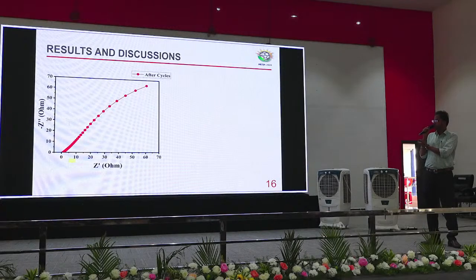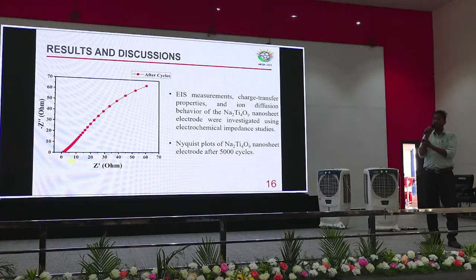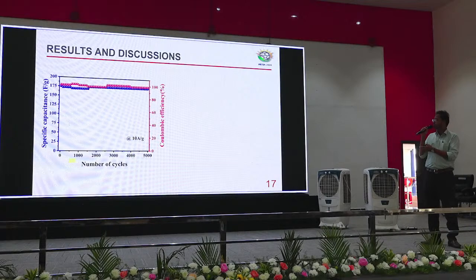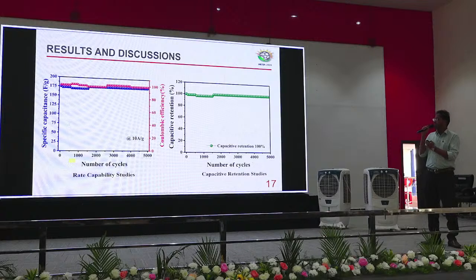So after that we move on to impedance studies. After finishing 5000 cycles, we get the Warburg region from those studies, and the Nyquist plot was calculated. Then we move on to rate capability studies. For rate capability, we use 10 ampere per gram, a higher current density, and cycle for 5000 cycles, and we get 100% Coulombic efficiency. Then capacity retention is around 100% and Coulombic efficiency around 97.9%.